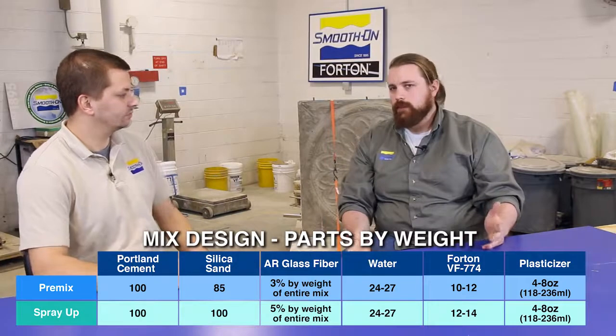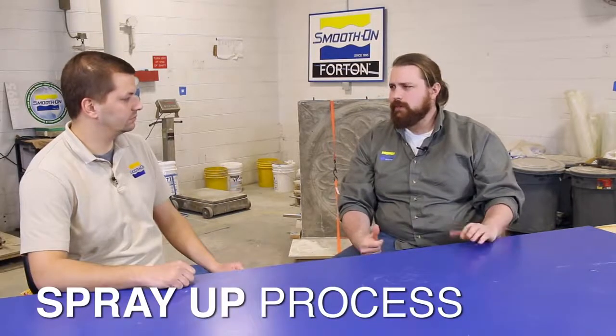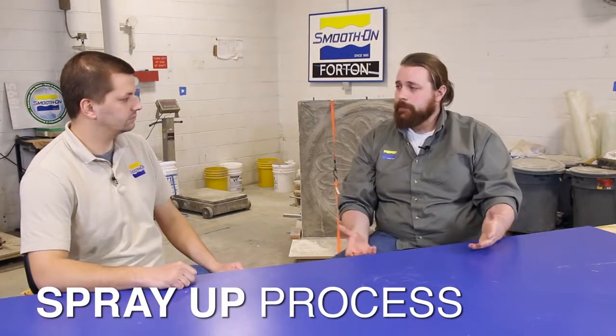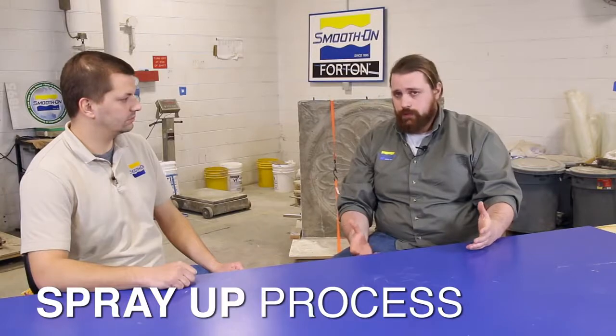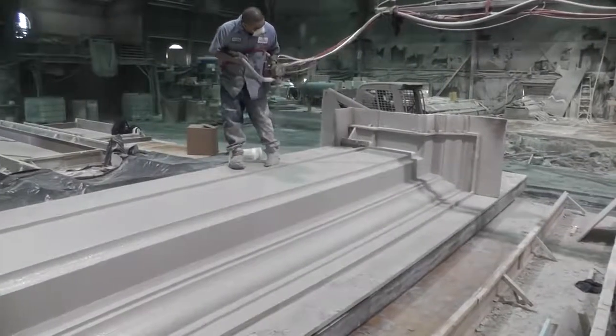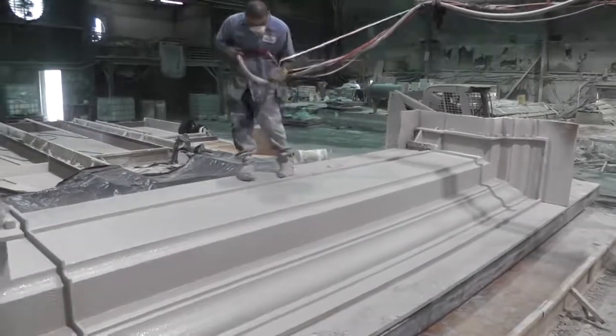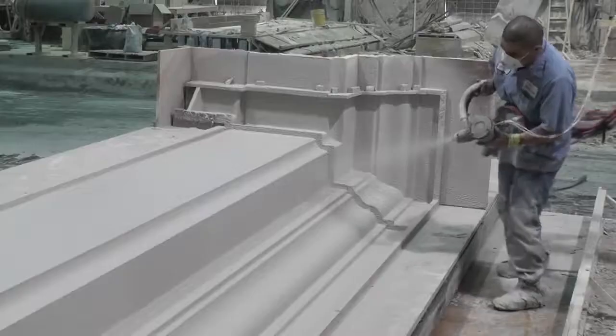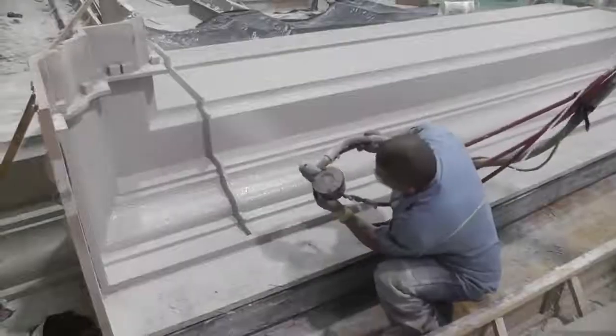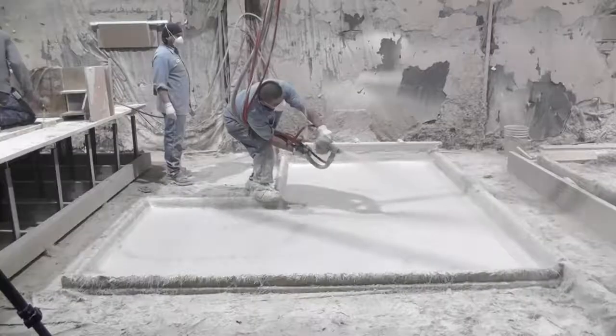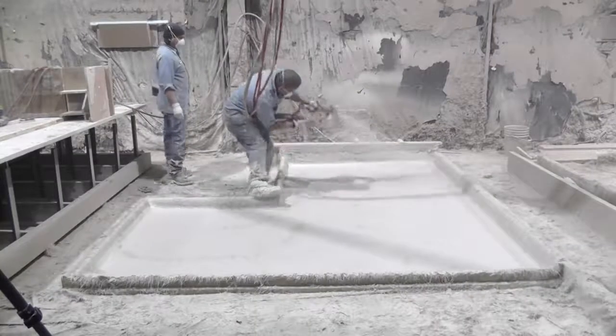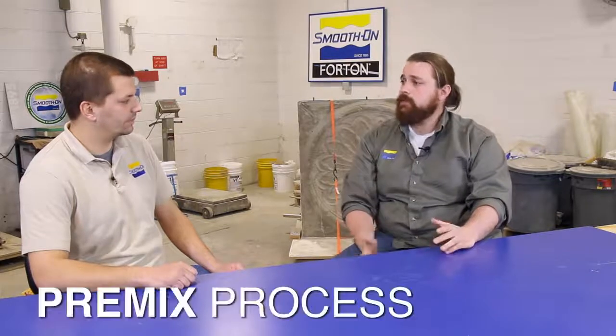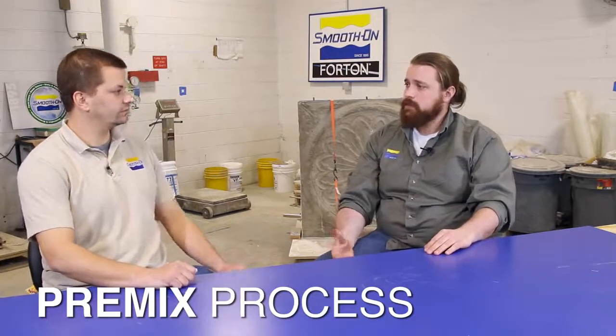Sure. Well, let's start with spray up, which would probably be less typical for the majority of users. Spray up application is used by high-end producers, generally speaking, and this is when you have large volume spray equipment and you're actually not mixing the fiberglass into the cement slurry. You're going to use a gun that actually chops the fiberglass separately and sprays the cement at the same time. That kind of high-range equipment, that type of process we showed from those two videos from GFRC Cladding down in Texas, to make those very large architectural panels. So that's pretty common from there. But more common for the small, medium, and even some larger users is the premix mix design and premix process. So tell us a little bit about that.